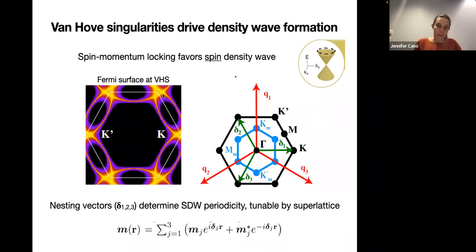And so if we have these Van Hove singularities at the K and K prime points, the spin at each of these points is going to be different. And so coupling these different points to each other is going to be coupling different states that have different spins. And so naturally, a spin density wave is the natural instability that you would expect. So what we did was look for a spin density wave instability of the following form. This is just some kind of magnetic order, but the wave vectors that appear in here are exactly the vectors that are separating these different Van Hove singularities. And so that will determine the periodicity of the spin density wave. And I want to emphasize that the spin density wave, if it does have an instability, is tunable. Its length scale is tunable by changing the length scale of this periodic potential. So that's another neat feature that comes out of this.